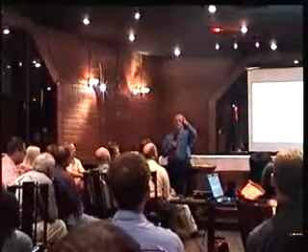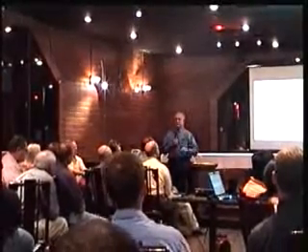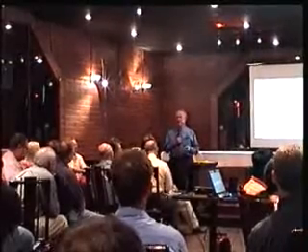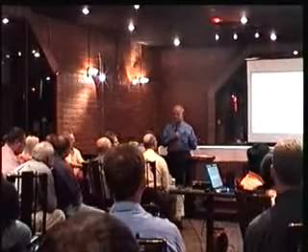Okay, the second task we had: now we generated a POD curve. What number did we report? We looked at the data, where all of the curves started near 100%, and then came to some point and started to drop off rapidly, the inflection point of the curve. We noticed that that was characteristic of all of the data and all of the curves that we had generated.